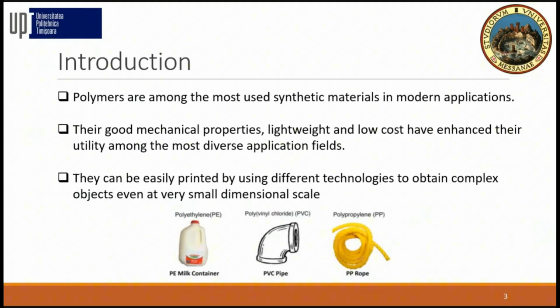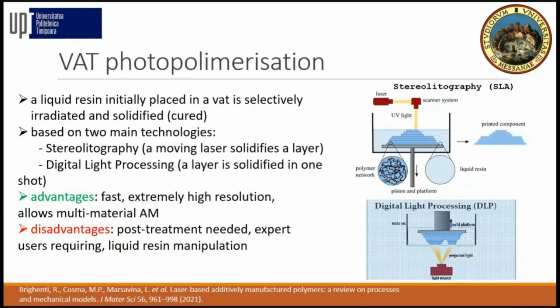From the point of view of manufacturing, they can be easily printed using different technologies, using additive manufacturing methods. So we use VAT photopolymerization. For this technique, the resin is in a liquid stage firstly, and then it stays in a vat, and then is selectively solidified either by a moving laser, which produces an ultraviolet light, or by digital light processing. Usually an LCD is used, and this solidifies one layer at one shot.